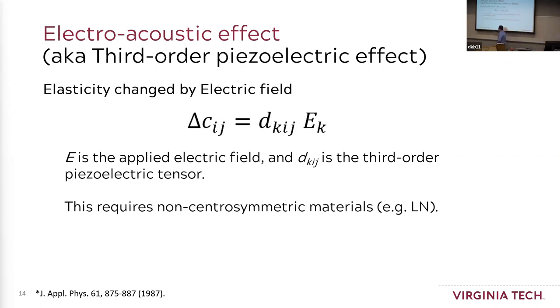It's been studied almost 35 years ago. It is that for certain materials, if you apply an electric field to the material, the elastic constant of the material will change. When the elastic constant or the Young's modulus of a material changes, you can imagine the phase velocity, or how fast the acoustic wave propagates, will also change accordingly. And to have that effect, we do require the material to be non-centrosymmetric, which this one is. So if you think about silicon, it's a centrosymmetric material, it won't have this effect. That's something we learned.